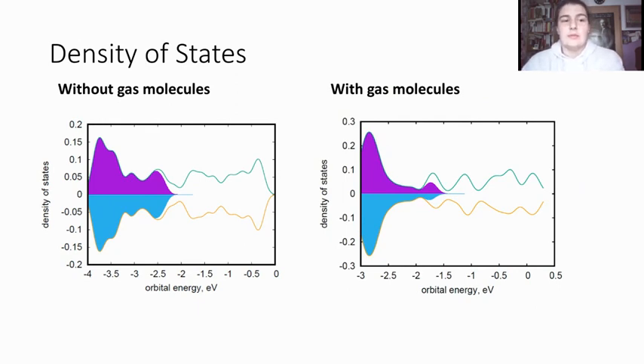And to start with the results, I would like to show the spin polarized density of states. On the left side, you can see the density of states for the model without gas, and on the right side with the gas molecules. And on both models, you can see that there's no band gap, so the conduction band overlaps with the valence band. And in both cases, the model behaves as a conductor.